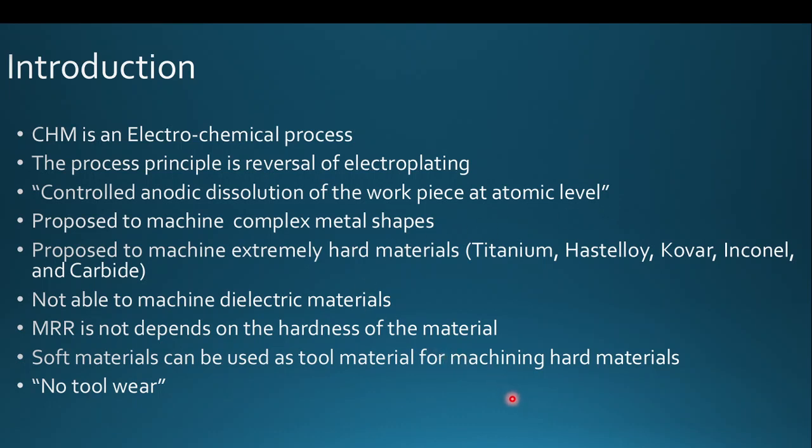This process is proposed to machine extremely hard materials like titanium, carbide, and other hard materials. There is no possibility of machining dielectric materials, because electrical conductivity in both the workpiece and tool is essential. Notably, the material removal rate is completely independent of the hardness of the material.